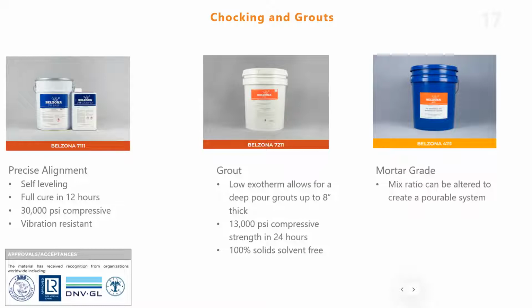And it's very vibration resistant. So the grout, also the 7211, has a little more lower exotherm. So it lets you get a little deeper pour, 8 inches thick at a time. Very often we compete with grouts similar to this. A lot of times you can only pour 2 to 3 inches at a time before you have to let it cook off and then re-pour. So with ours, you get a little thicker pour. And it's also very high compressive strength, 13,000 PSI in 24 hours. And these are all solvent free.